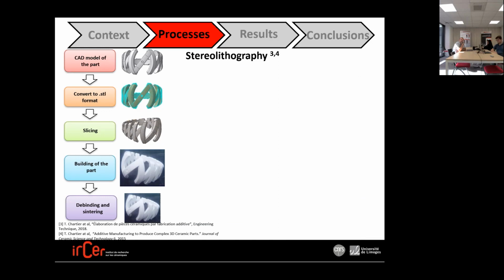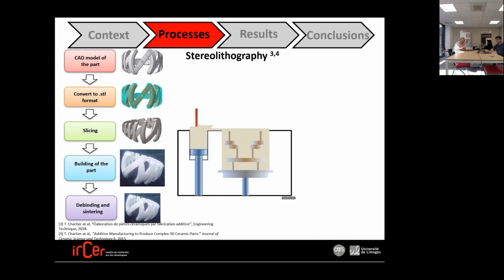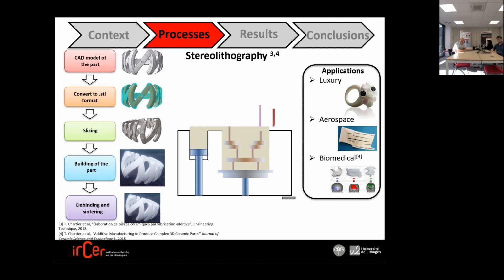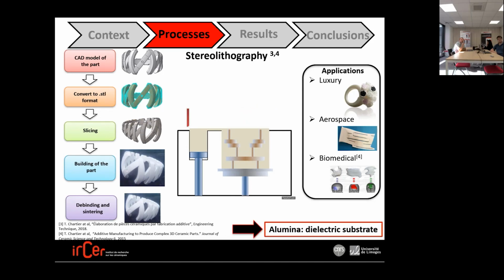Just a little focus on the stereolithography. It has been presented before. We first have to use a CAD model of the part. We have to convert it to a standard STL format. Then we slice, sorry, we build it, and after that we have to debind and sinter the part to obtain a finished part. As presented here, at each slice we make a layer thickness of about 50 microns, and then we have to polymerize the paste to make the shape we want in the slice. Some applications are in luxury, aerospace, or biomedical. This process is used to obtain the dielectric substrate, which is made of alumina.